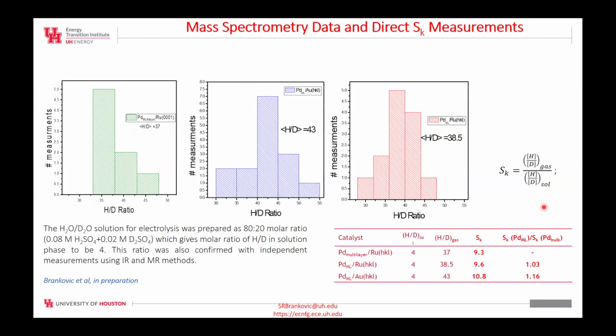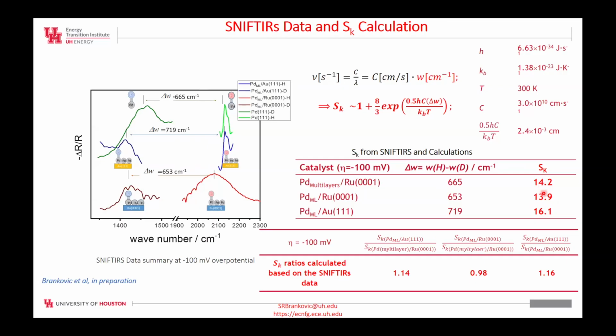It turns out that palladium monolayer on gold has the highest one, then palladium monolayer on ruthenium, and palladium multilayer on ruthenium, which is bulk palladium, very close. This probably means that compressive stress on ruthenium is not significantly affecting the activity of the palladium monolayer. What is really important in the fundamental sense is the ratios here. If you normalize with the palladium bulk as the reference, you can see that palladium monolayer on ruthenium underperforms, while palladium monolayer on gold is better than bulk palladium by about 15%.